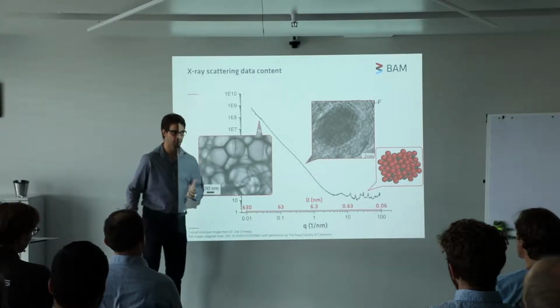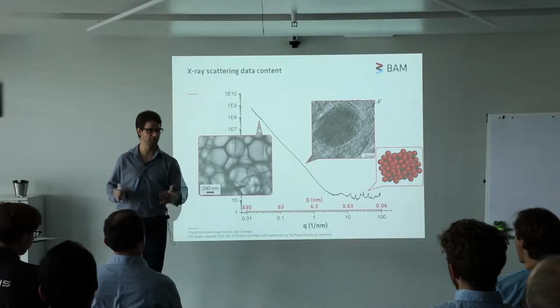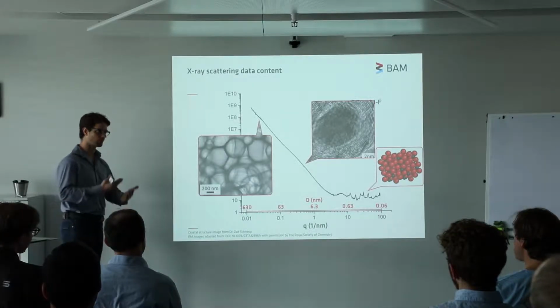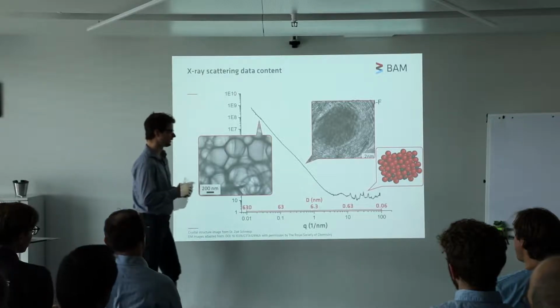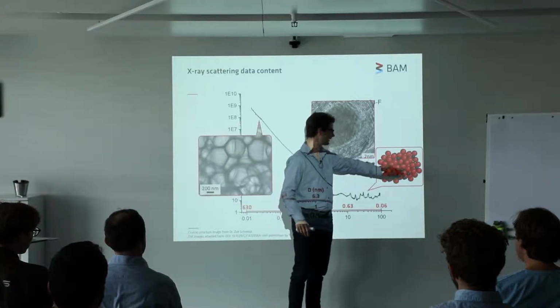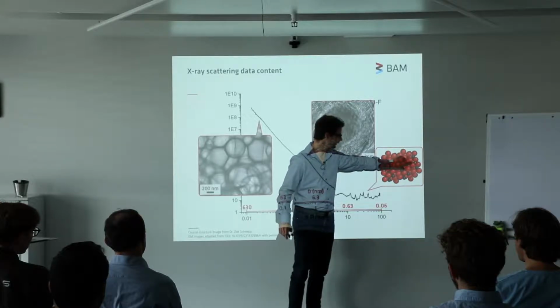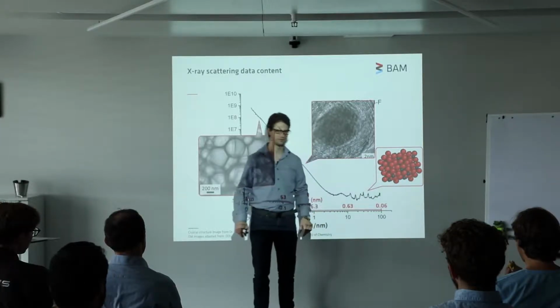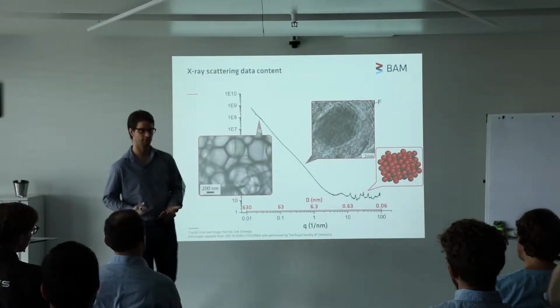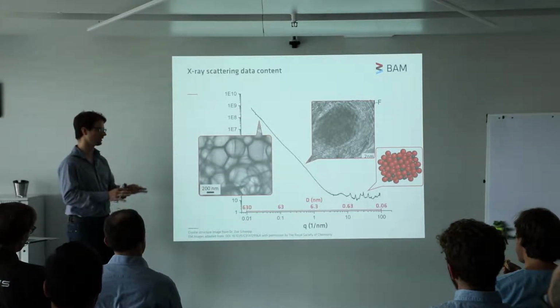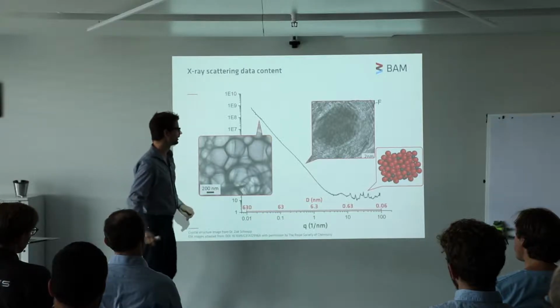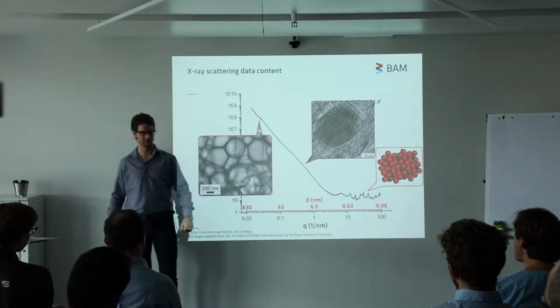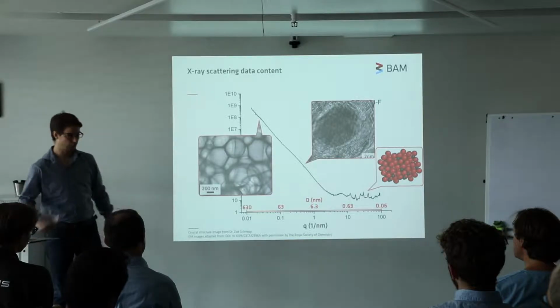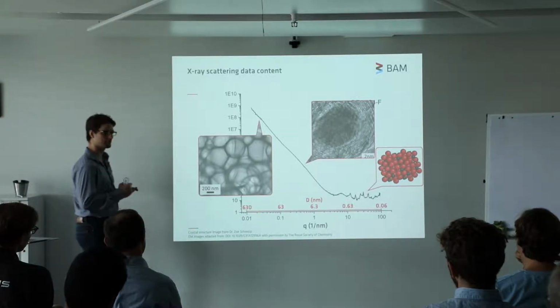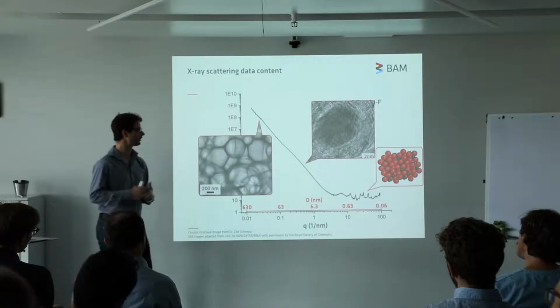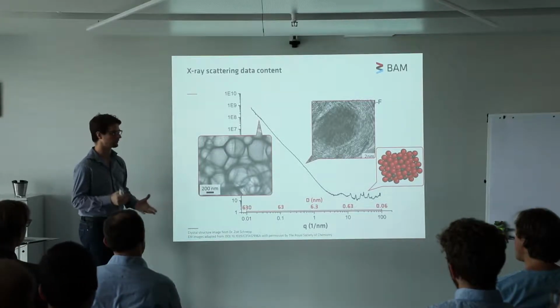Note, however, that in principle, when I say contrasting objects, it means anything with an electron density contrast, whether or not it's regular. So for things like crystal lattices, you have lengths which appear very often, and that's why you get these very nice diffraction peaks. But even for completely amorphous materials, if you have an amorphous nanoparticle in solution, you would still see an X-ray scattering pattern. You'd be able to derive from that what the size distribution is and what the volume fraction is of these particles that are floating around in your dispersant.